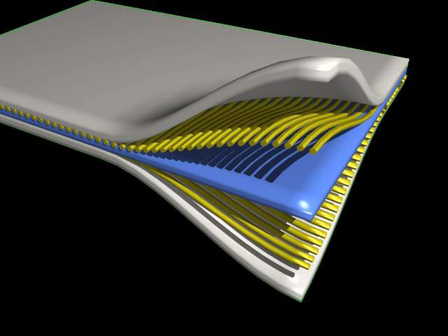The upper mold is installed and vacuum is applied to the mold cavity. The assembly is placed into an autoclave. This process is generally performed at both elevated pressure and elevated temperature. The use of elevated pressure facilitates a high fiber volume fraction and low void content for maximum structural efficiency.